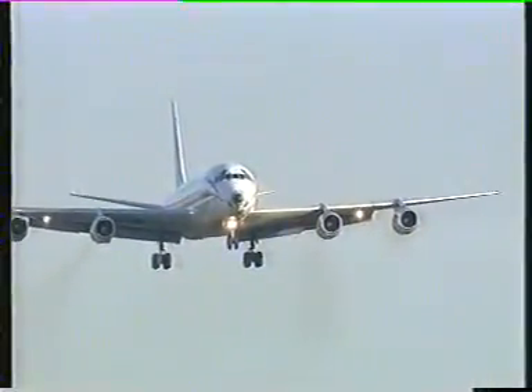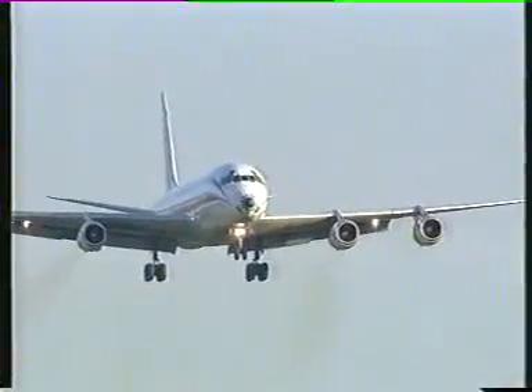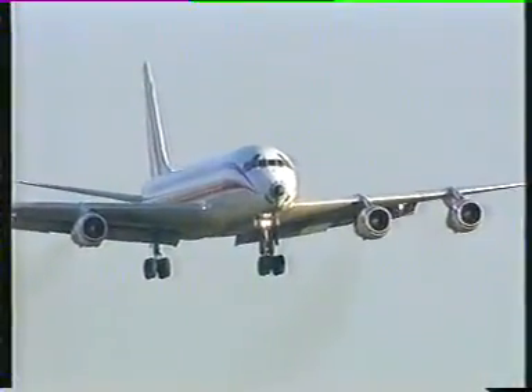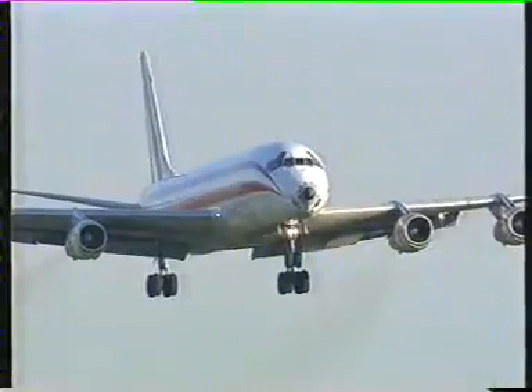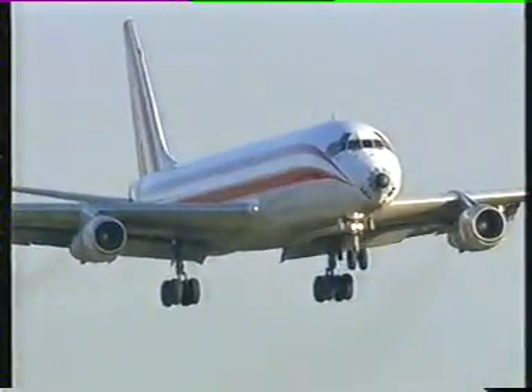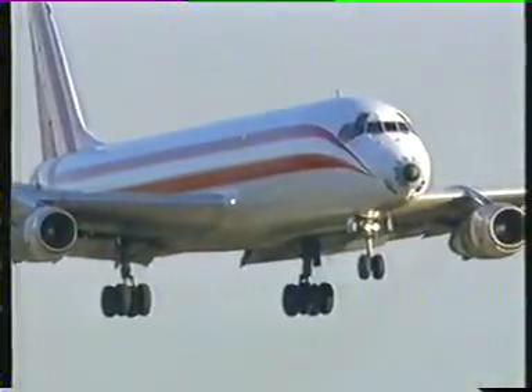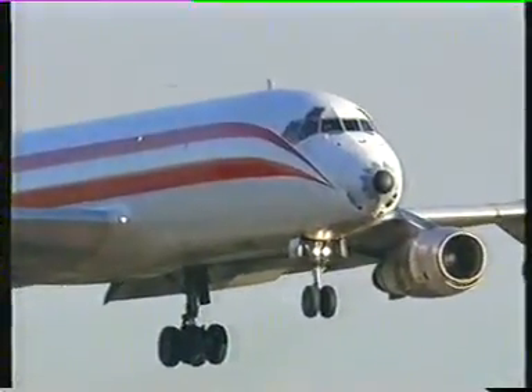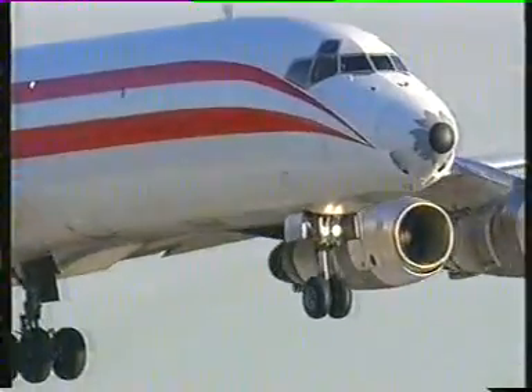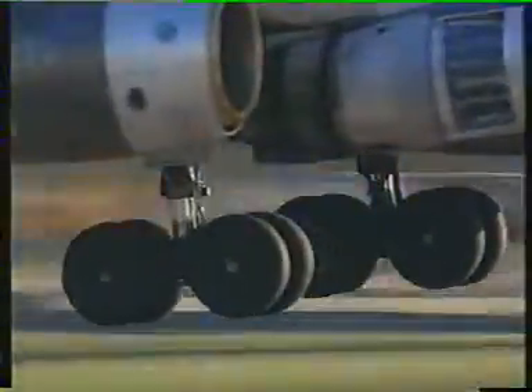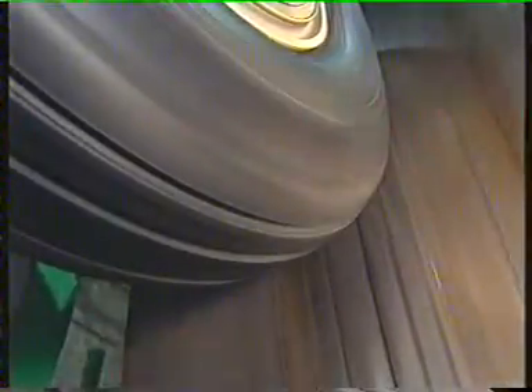You're about to witness an aircraft tyre during one of its most rigorous moments of the flight. Within seconds of touchdown, each tyre will have accelerated from 0 to over 100 miles an hour. All that energy has to go somewhere, and the temperature may rise from -40 to 100 degrees Celsius. All that while carrying a load of up to 30 tons. The tyre deflected slightly and smoke was given off with the heat, but this is quite normal in a successful landing. So how does it do it?